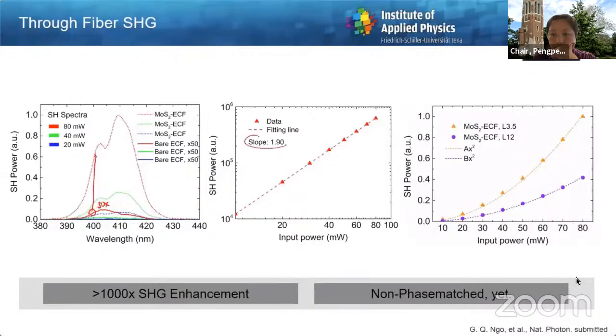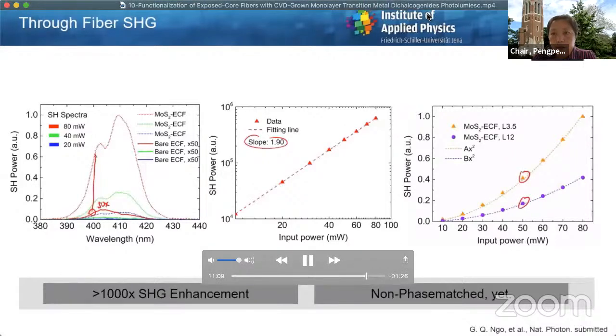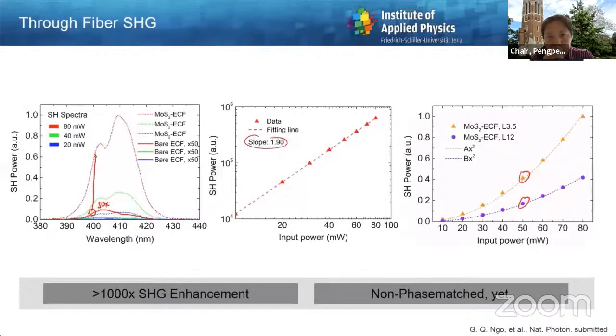We also see nice kind of power dependence with a slope of 2. Yeah. Funnily enough, we see more second harmonic light coming from a shorter piece of fiber as opposed to a longer piece of fiber, which points to the fact that due to the very, very dense coverage of the fiber with these crystals, we are actually somewhat limited by the optical loss in the second harmonic. Moreover, our system is not phase matched yet at the moment. So we believe that if we go to a regime where we have phase matching, currently investigating various methods to do so, that we may see another 3 or maybe 4 or 5 orders of magnitude enhancement in the second harmonic yet.